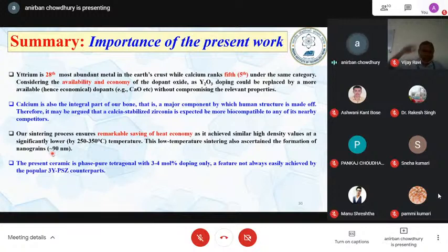And even if you take today the yttria from Tosoh or Sulzer Metco at 3-4% mole doping, you see a phase mixture of monoclinic plus tetragonal. If you take our powder at 3-4%, it is phase pure tetragonal. Exactly what you need for all the properties involving mechanical applications.